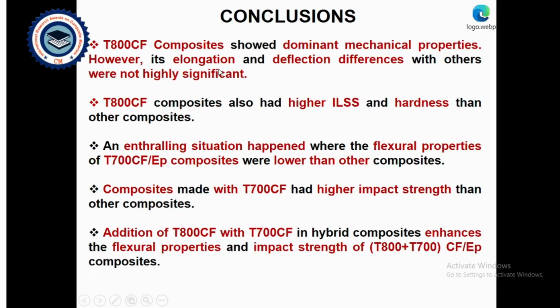Conclusion: T800 composite showed dominant mechanical property. However, its elongation and deflection difference with others were not significant. T800 composites also had higher interlaminar shear strength and hardness than other composites, whereas the flexural properties of T700 carbon fiber composites were lower than the other composites. Composite with T700 carbon fiber had higher impact strength than the other composites.